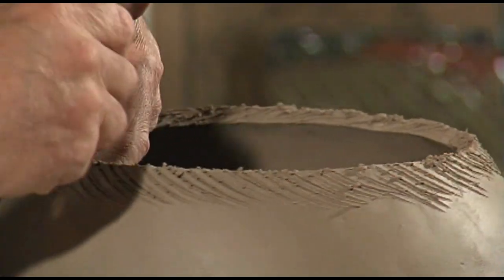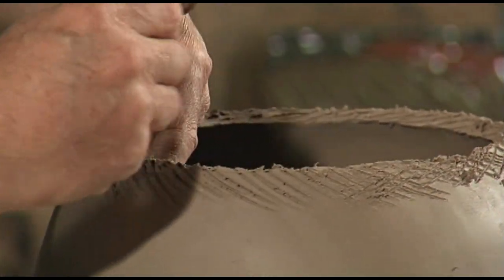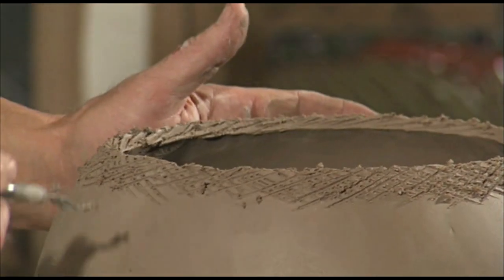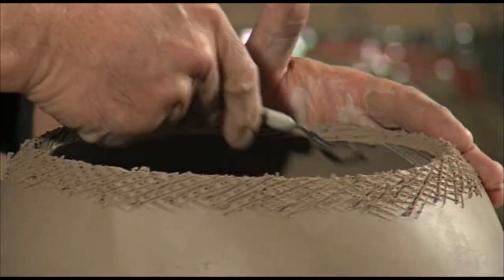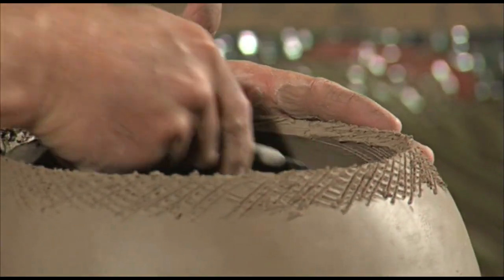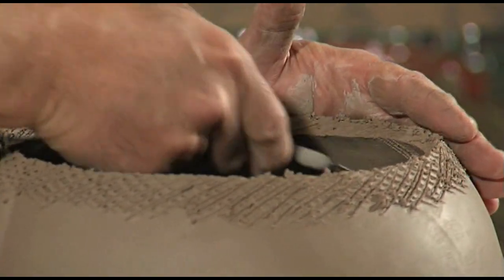And I believe that by making it smooth and of uniform thickness, as thin as I can get it, yet for it to maintain its strength, because you are banging on it. So if you get it too thin, it will crack. I think it's a little more than a quarter of an inch thick. I measured, and they were pretty consistent, 0.8 centimeter thickness.